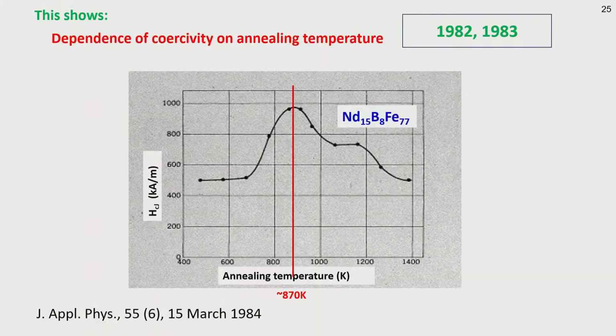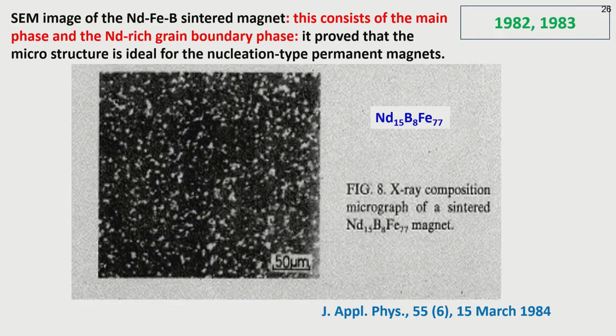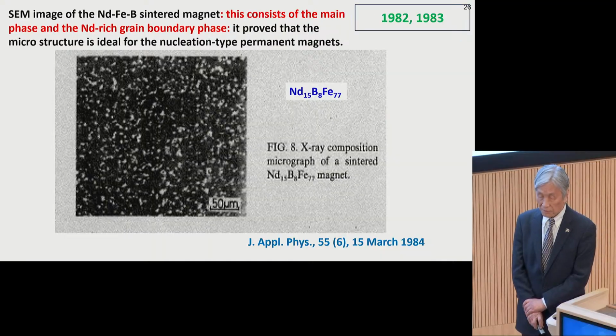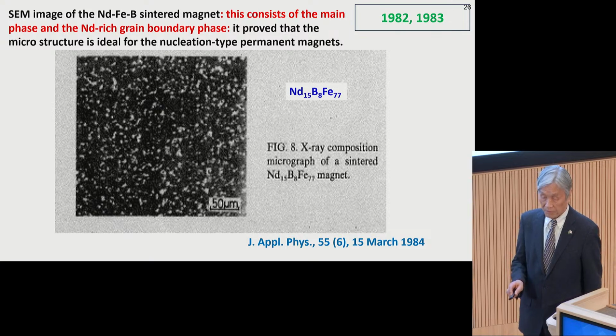And this shows the dependence of coercivity on annealing temperature. Coercivity shows a peak value at 870 K. And this shows SEM image of the neodymium iron boron sintered magnet. This consists of the main phase and the neodymium rich grain boundary phase. It proved that the microstructure is ideal for the nucleation type permanent magnets.